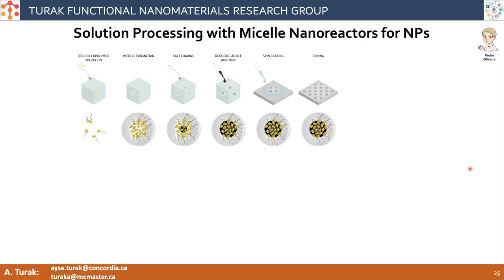And the typical way that we would do this is to use spin coating, right? We want to get a nice uniform array. These arrays are typically formed by the self-assembly of these hard-shell spheres. Right? So you can imagine taking sphere beads and shaking them in a box. The optimal configuration is a hexagonal close-packed system. The same kind of thing is happening when we deposit them on the surface.